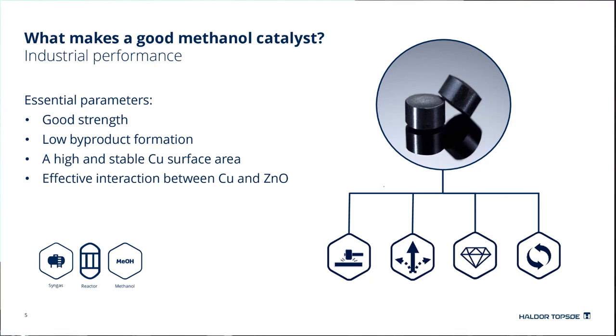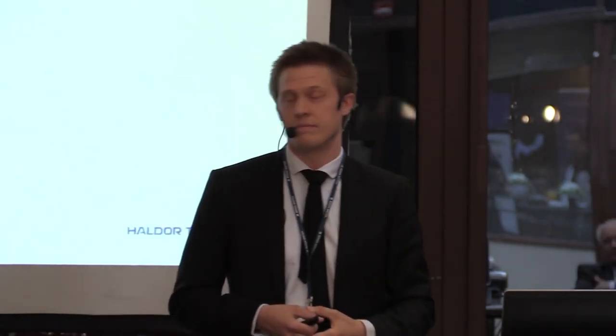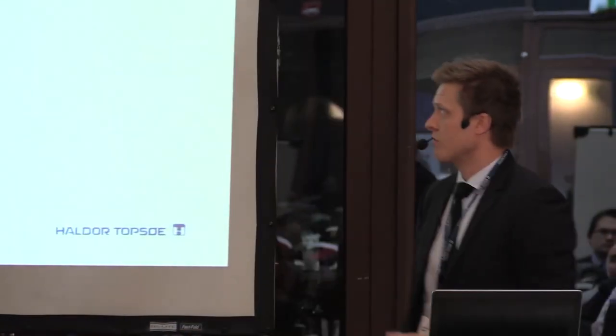There are some key characteristics that make a good methanol catalyst. And here there are 4 really essential parameters. First of all, you need really good mechanical properties of your methanol catalyst. In the oxidized state, or the fresh catalyst, it actually needs to withstand being dropped from 10 meters height when it's loaded into these huge boiling water reactors. But also in the activated state, the methanol catalyst needs to withstand the static force of the pressure drop over these types of reactors. Then, of course, you need a very selective catalyst.